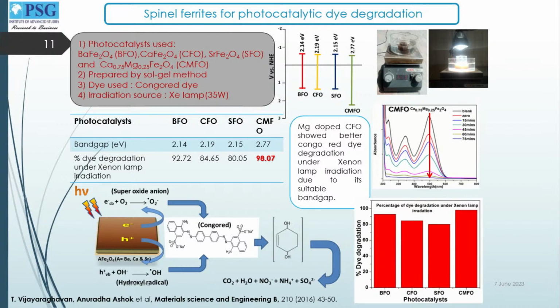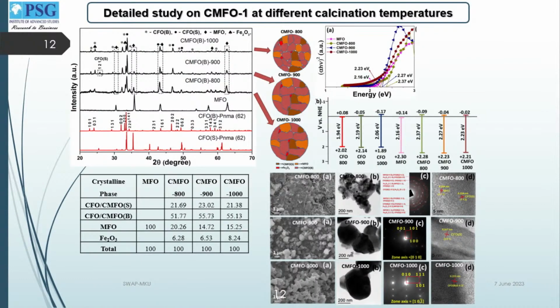With calcium ferrite, we tried to improve its degradation capability by doping with magnesium, and we found the highest dye degradation. So we identified it as the best performing photocatalyst, and we tried to work more on this magnesium doped calcium ferrite. When we synthesized it, we calcined it at different temperatures. We obtained several phases. It was a multi-phase mixture when we heat treated the Sol-Gel synthesized calcium ferrite.